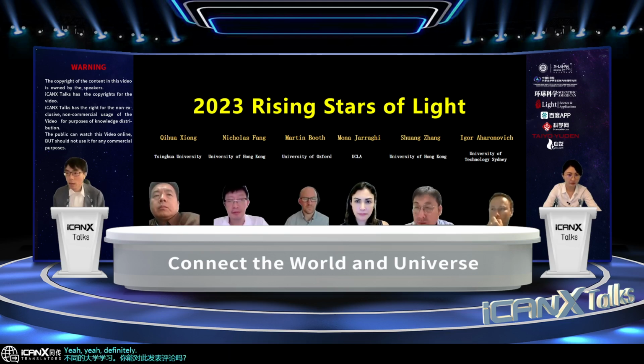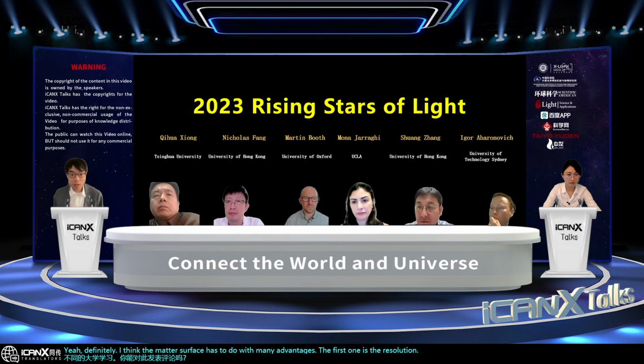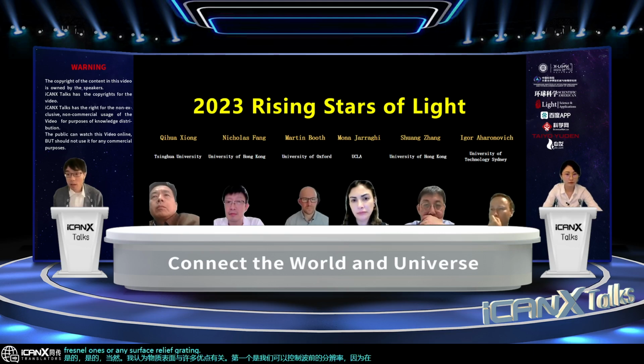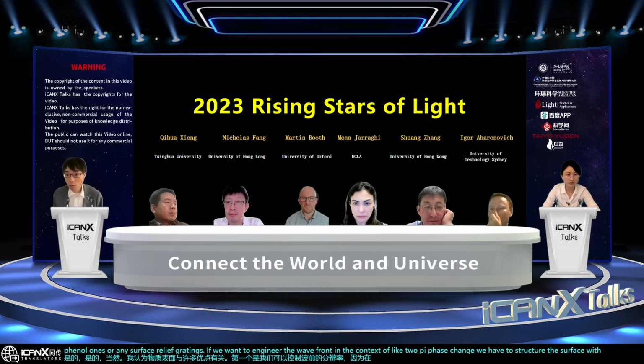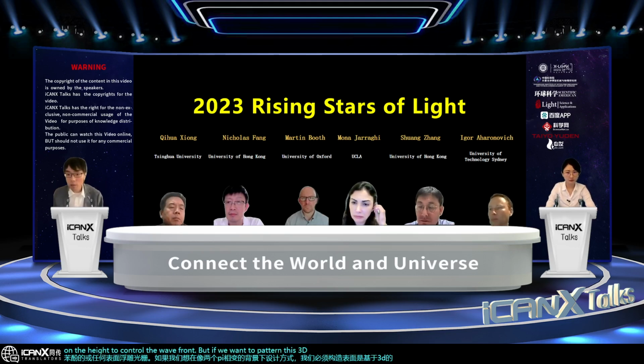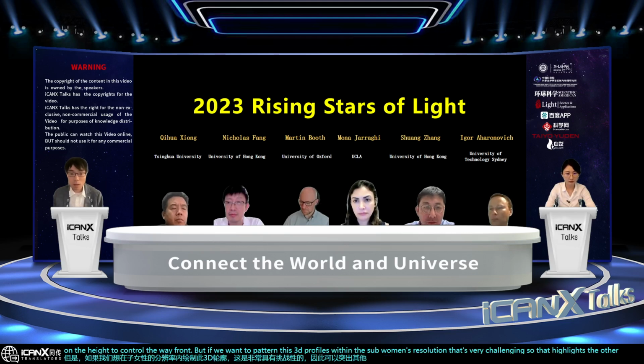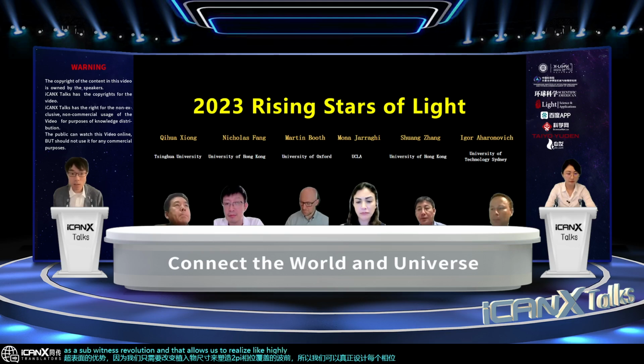Well, definitely. I think the metasurface has many advantages. The first one is the resolution. We can control the wavefront because in the context of a Fresnel lens or any surface relief gratings, if we want to engineer the wavefront in the context of a 2 pi phase change, we have to structure the surface in 3D, relying on the height to control the wavefront. But patterning these 3D profiles at sub-wavelength resolution is very challenging. That highlights the advantage of the metasurface, because we only need to change the meta-atom dimension to shape the wavefront over 2 pi phase coverage. So we can really engineer each phase front at sub-wavelength resolution, and that allows us to realize high-end metalenses and holograms with a large field of view.